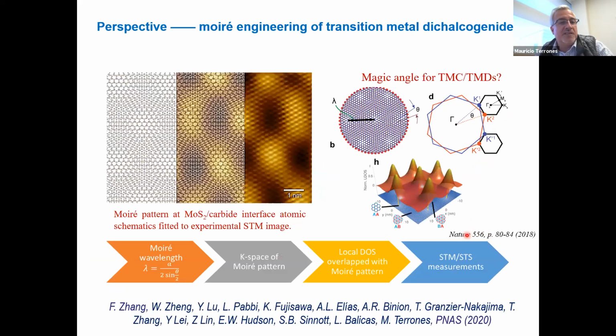So this is the moiré pattern that we believe is happening: you have hexagons eclipsing each other, but they are of different sizes. So the moly sulfide hexagons are different from the continuous moly carbide hexagons, and this is the pattern that we see. This is the two patterns overlapped theoretically. This is the overlapping of both, and this is the experimental one. So this is a good overlap.